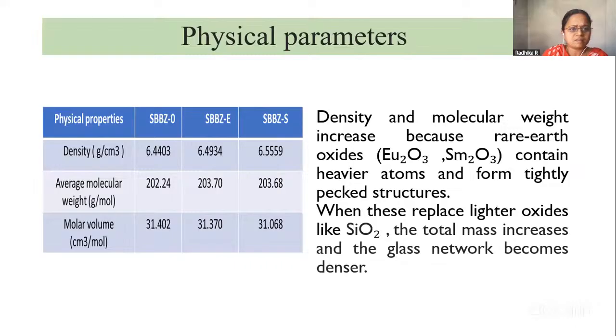By observing this, density and molecular weight increase because of the rare earth oxides; heavier atoms form packed structures. When these replace lighter ions like silicon dioxide, the total mass of the glass network is denser. By observing the table, without doping, the density is 6.44 grams. After